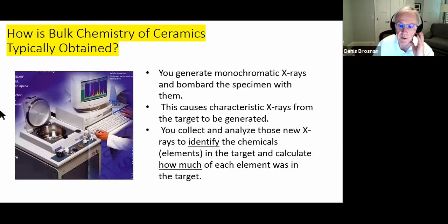On to X-ray fluorescence. How do we obtain that? Well, we obtain it in an instrument that generates X-rays and bombards the specimen down in a specimen holder within the instrument with X-rays that puts energy into the elements in the target where the X-rays are striking, and the target emits characteristic X-rays. Characteristic means they're X-rays of given wavelength or energy. So these X-rays are generally monochromatic, meaning one wavelength, that hit the target, and then the target itself, the ceramic that we're analyzing, emanates or releases other X-rays that are characteristic of what is in the target. So we can take those X-rays that are given off and analyze them as to energy or wavelength, and we can figure out what's in the target. And the intensity of radiation coming off of the specimen tells us how much is there.